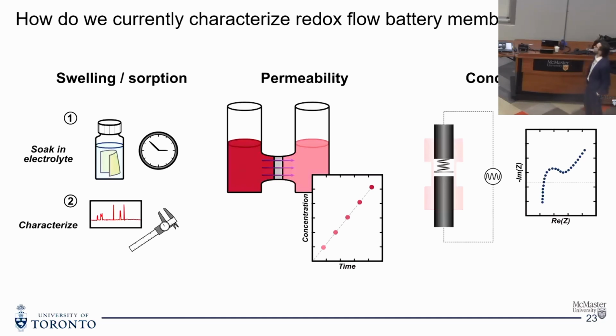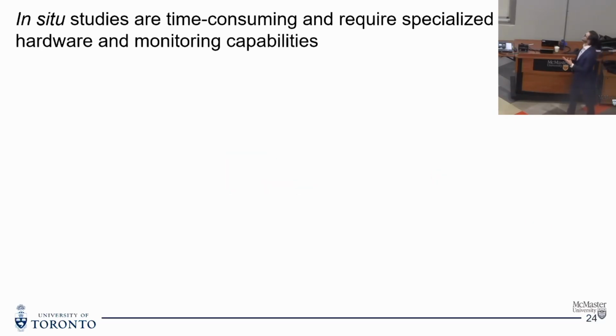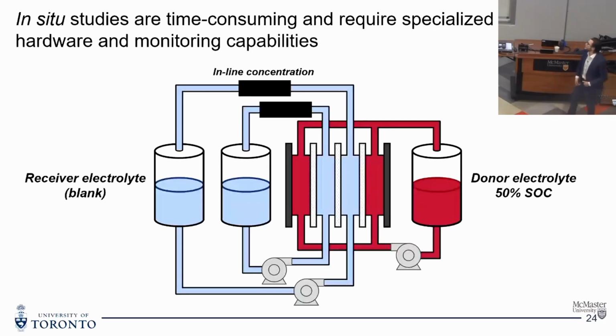So we want to think, how do we measure or characterize a membrane under electrochemical conditions? There you would look to something like an electrodialysis cell, where you would measure it in situ in a setup that looks kind of like this, where you have multiple receiver electrolytes and a donor electrolyte that contains your active species. You can apply a current across this, see how the ions move through the membranes, and then measure the concentration of those species. This looks closer to the setup we envision, but it's pretty tedious. We have to measure the concentrations constantly. It's a lot of sampling. It's almost a cell, but we have all these extra chambers. So it's still not quite there.